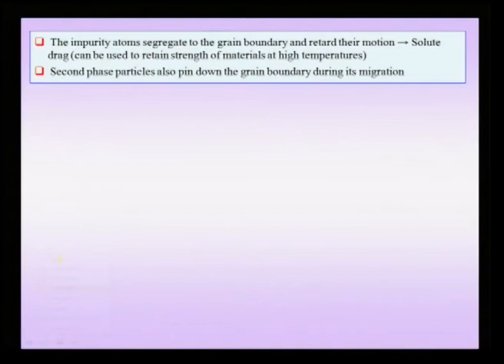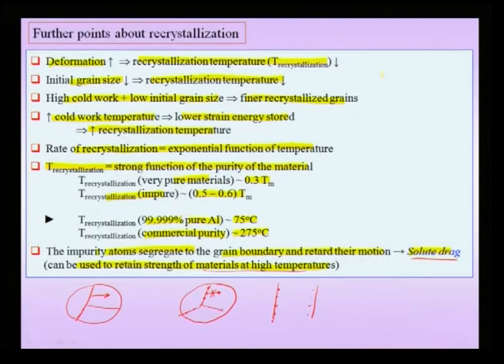So, as I pointed out, let me repeat this. The impurity atoms segregate to the grain boundary and retard their motion. This process of solute drag can be used to retain the strength of materials at high temperatures. Apart from, of course, solute atoms, you may also have second phase particles or precipitates which sit at grain boundaries, which also may retard the motion of grain boundaries.